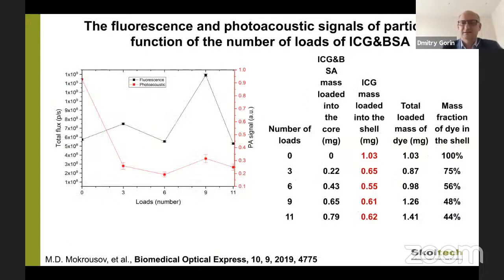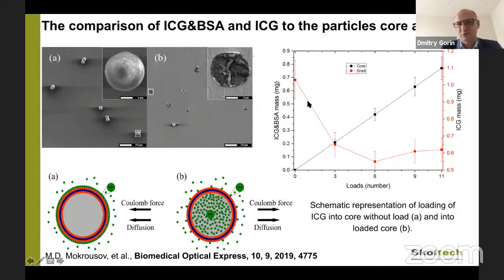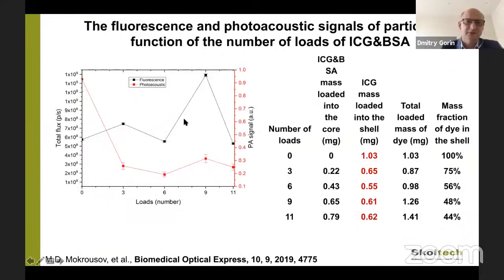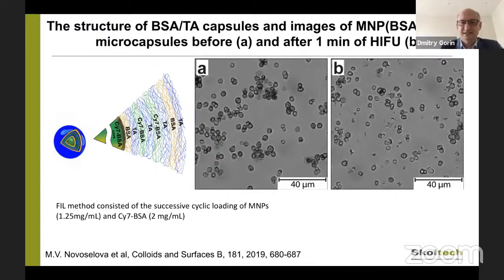And the interesting result that we have obtained is that the optoacoustic signal is completely proportional to the concentration of the dye inside of the shell, not the whole concentration of indocyanine green, but exactly the concentration that we have in the shell. This is a very important result. It means that we have free volume inside for encapsulated drugs, and we demonstrate that we can use high intensity focused ultrasound to destroy such a type of shell.